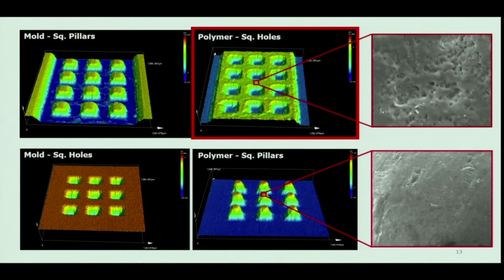And the failure in replicating the nanostructure on top of pillars is due to the fact that the polymer cannot penetrate the holes completely in the mold because the air gets trapped. And that's why no nanostructures can be seen on top of pillars in the plastic.